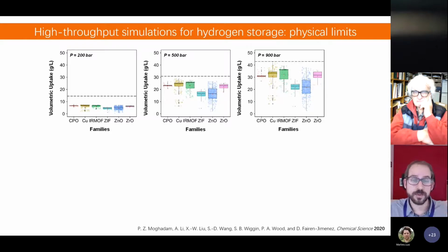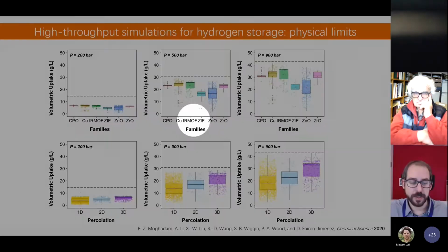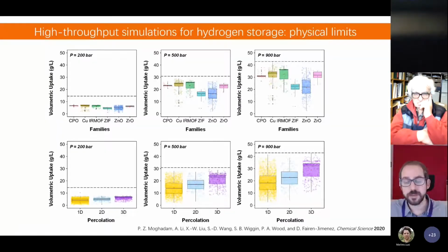So this helps us to identify the best materials and the best families for specific applications if we want. It is a lot of knowledge that we can really take into account. Looking at the volumetric capacity and the percolation theory, if we have materials with one-dimensional channels, two-dimensional porosity, or three-dimensional networks, you can see that on average, three-dimensional materials perform much better than one-dimensional structures. So if I need to choose one without knowing more information, I'm probably looking for three-dimensional networks in this application. This is an example of how statistical analysis and big data can help us to identify the best materials.